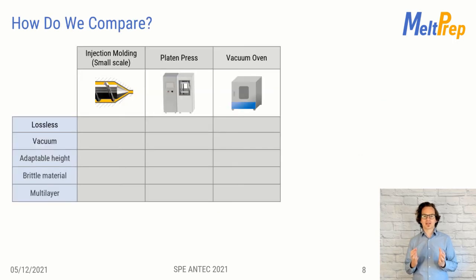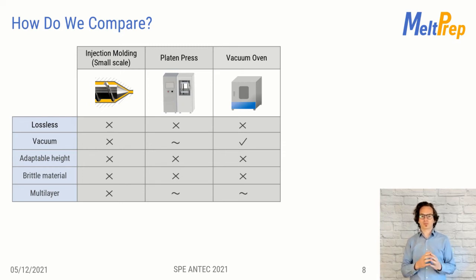Most of you probably know multiple methods to prepare samples. We compared their performance. In conventional preparation approaches like injection molding, viscous dissipation and strong extensional flows can cause thermal or mechanical degradation. Air voids or possible moisture inclusions often remain within the sample, harming subsequent experiments or measurements. Or you may even face another difficulty. Have you ever tried to die cut an amorphous, brittle material? It will just scatter and leave you with 1,000 pieces.